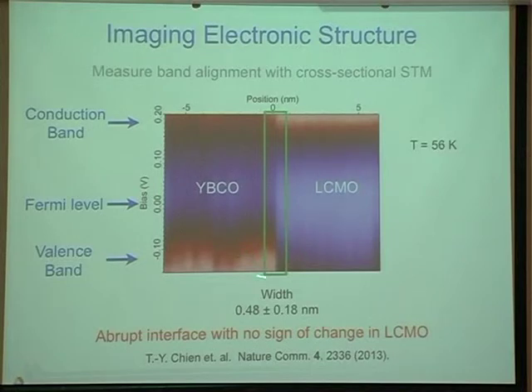And what did we find? Well, what we found was that electronically, this interface is extremely sharp. We came up with a width of 0.5 nanometers. It's literally an extremely sharp interface. The other nice thing is we can see, for example, the band alignment.